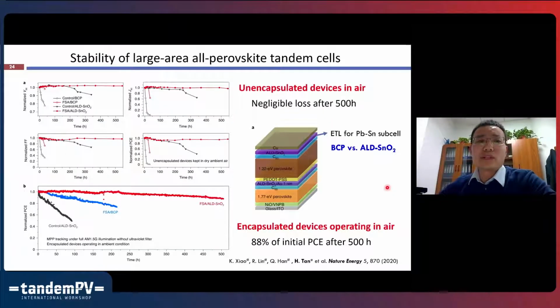We also tested the stability of these all-perovskite tandem devices, and we found that the ETL, the electron transport layer of the narrow bandgap subcell, is quite critical for the stability. For example, if we replace the organic molecule-based ETL, BCP, with atomic layer deposited tin oxide, it can maintain a good efficiency even without encapsulation in the air. After 500 hours of storage in the air, the device performance can still maintain their initial performance.